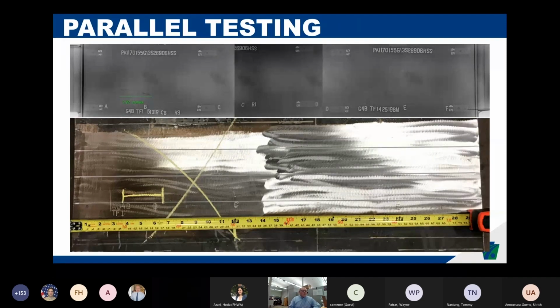So here's another example. In this one, you can clearly see a 3-inch radiographic reject, but in this case, it's what you can't see that was kind of interesting. Out in the middle of this joint, there's actually a flaw that was not found with radiography, which is somewhat expectable, right? They're 2 different processes. One might find things that others won't. It's a well-known fact that ultrasonic testing is better at finding lack of fusion discontinuities.